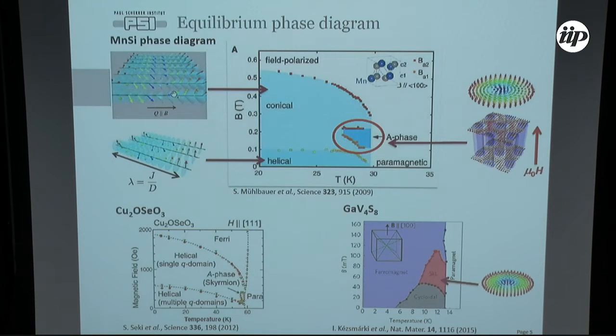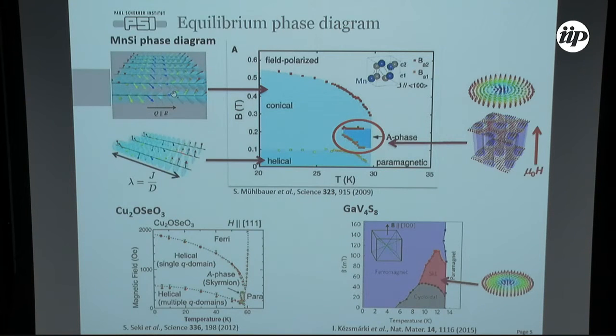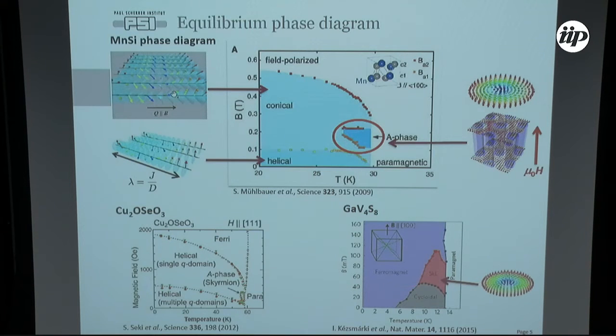This skyrmion phase was first reported in 2009, but in other materials with different structures, the phase diagrams are all remarkably similarly structured. Here is copper oxyselenide, which is an insulating material; even in this insulating material the skyrmion phase is only about two Kelvin wide. Even in the completely different Néel-type host material, the phase diagram is differently structured but the skyrmion phase is still found only close to the ordering temperature and under a finite field.